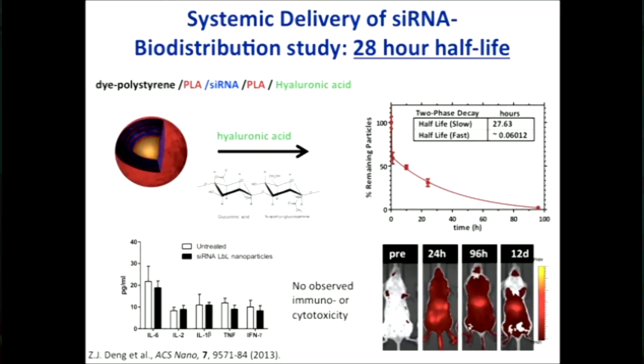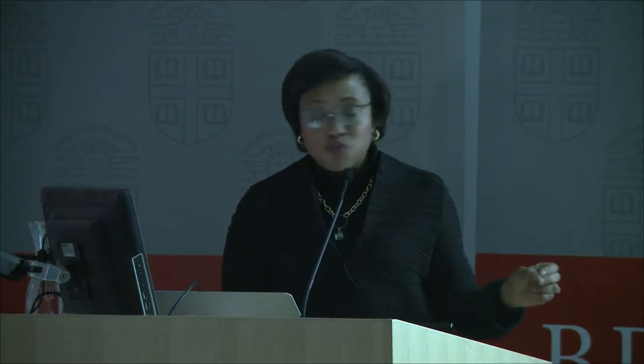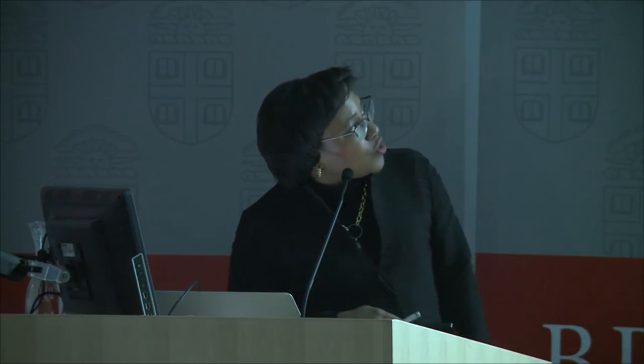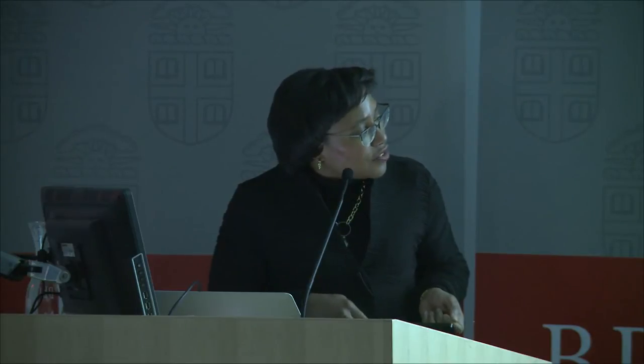First, we wanted to know whether or not they would go through the bloodstream for a long time or whether they'd just be eliminated rapidly. And it turns out that these systems have a really long half-life, 28-hour half-life, which for a number of nanoparticle systems is fairly rare. And we think it's because of this hyaluronic acid outer coating. So we can get this into the bloodstream and it will hang out there for a long time.